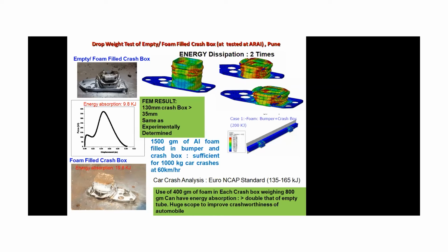And we also found that if you fill the crash box and bumper with aluminum foam and put this in the car's frontal area, and the car is moving at 60 kilometers per hour with a weight of 1000 kg, whatever crash happens, the foam and crash box absorb all the energy, and there is no damage to the structure, either the engine or the passenger.